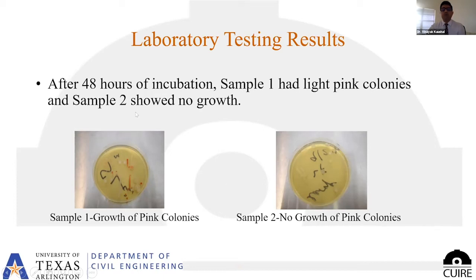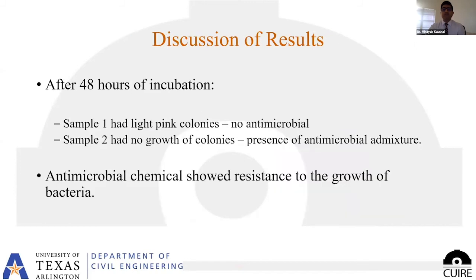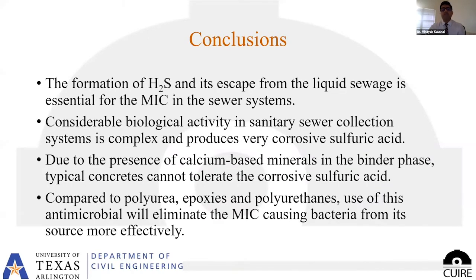After 48 hours of incubation, sample 1 had light pink colonies, as you can see, and sample 2 showed no growth, which shows that the antimicrobial acted against the building up of the colonies, which would have led to the corrosion. So after 48 hours of incubation, the antimicrobial chemical showed resistance to the growth of the bacteria.